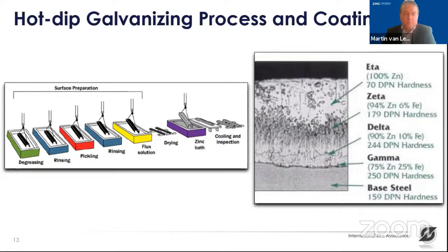You need to clean and prepare the steel surface first by degreasing it, removing all the oils and dirt on top. It needs to be pickled to remove all the oxides from the steel surface. After pickling, in a flux bath you apply a flux layer, which protects the steel surface against reoxidation and increases the reactivity with the zinc in the final zinc bath, which is normally kept at a temperature of 450 degrees Celsius. Once the steel parts are dipped into the zinc, a diffusion process starts.